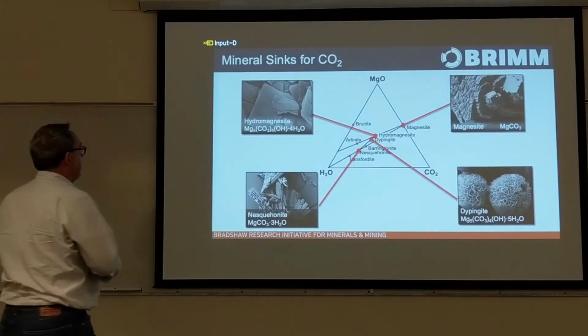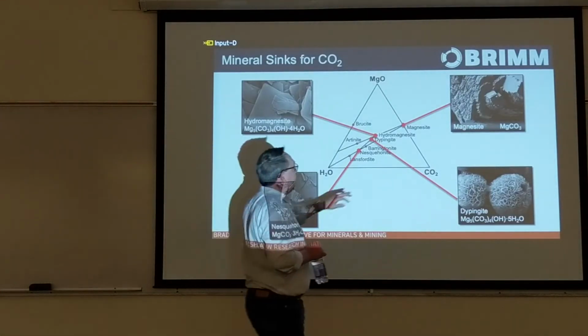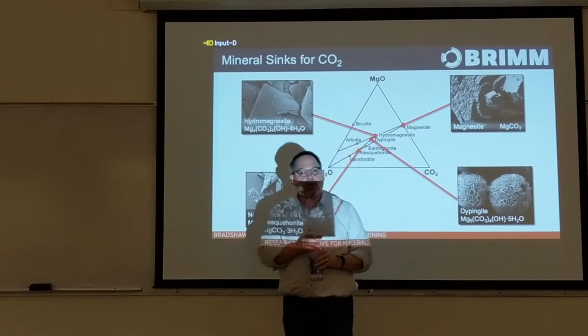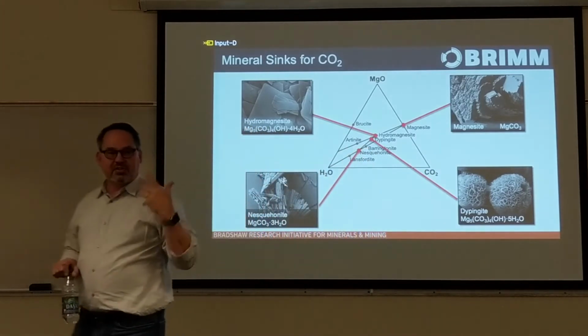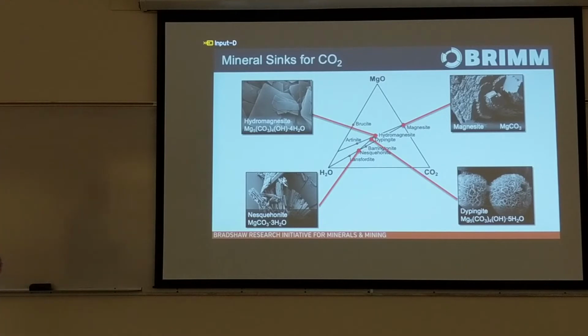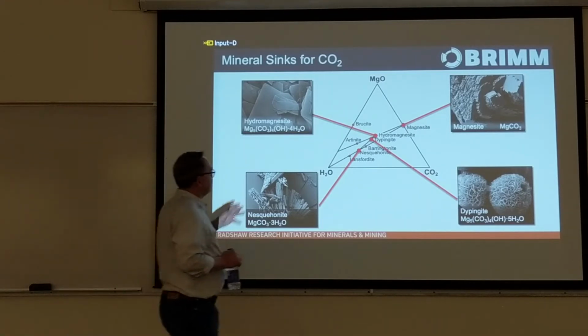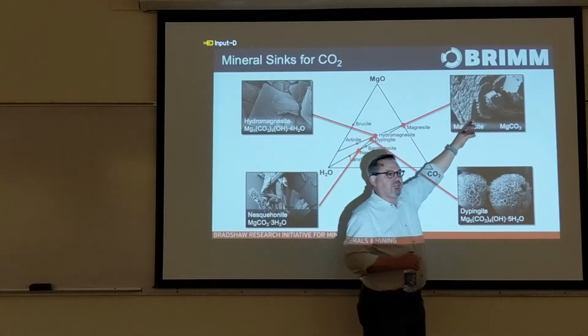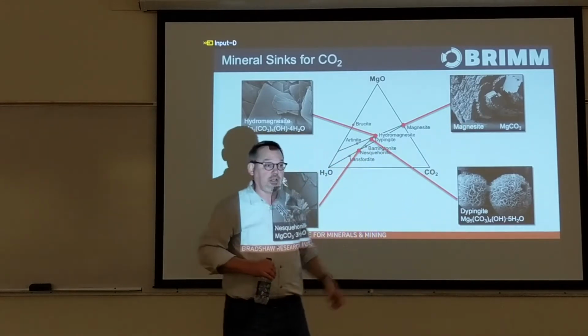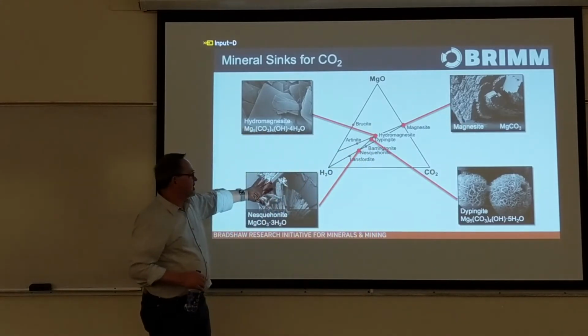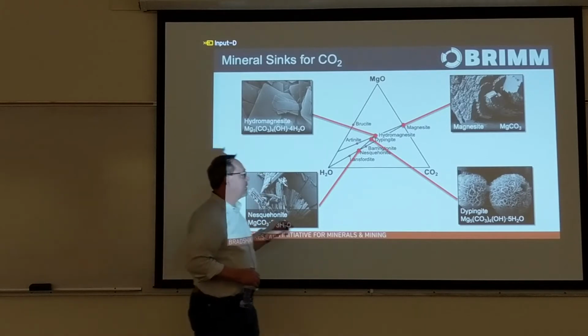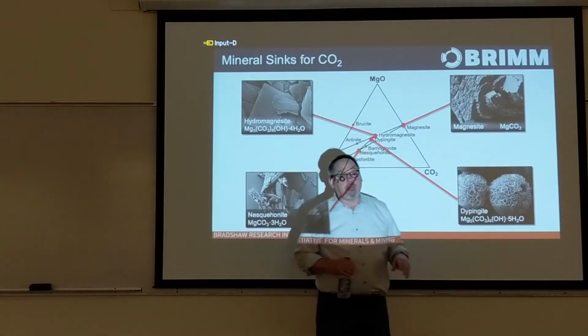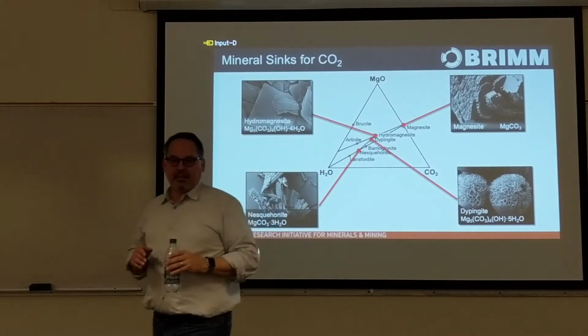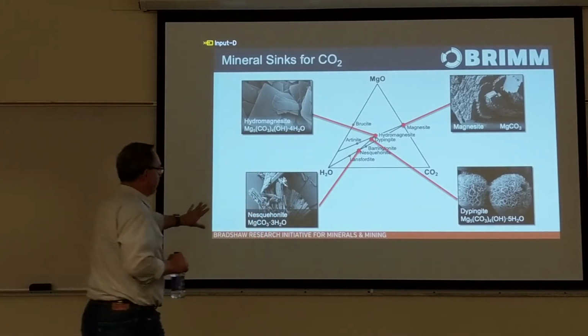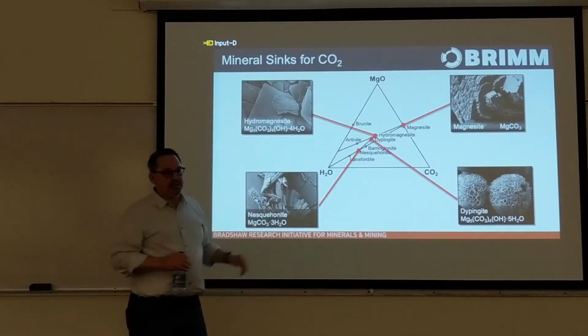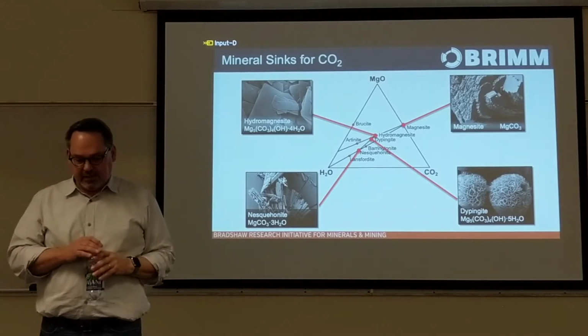And we're putting the carbon in carbonate minerals. This is what we would like to make, magnesite, an anhydrous magnesium carbonate. This is the mineral that's actually the most stable thermodynamic state for magnesium carbonate under Earth's surface conditions. But because of the strong solvation sphere around magnesium when it's in solution, we typically make hydrated magnesium carbonate minerals, and hydromagnesite, nesquehonite, and dypingite are all examples of the minerals that we actually find forming in the tailings. And they're the minerals that are doing the cementation.